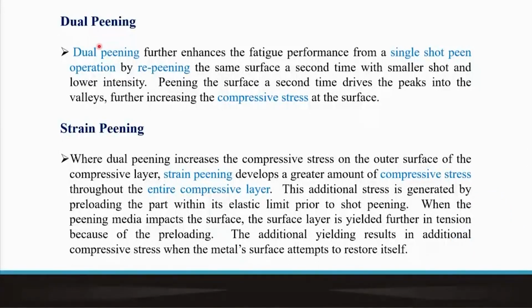In fact, it is also known that when we resort to such peening operations, instead of a single peening operation, that means using the shots of the same diameter in the same spraying operation, if it is actually repeated with another operation with smaller diameter shots or smaller diameter spherical balls, then actually the effect is even better. So, another variant of shot peening could be a possibility where the material is stretched, for example, either by subjecting it to some rolling operation or tensile stretching operation.